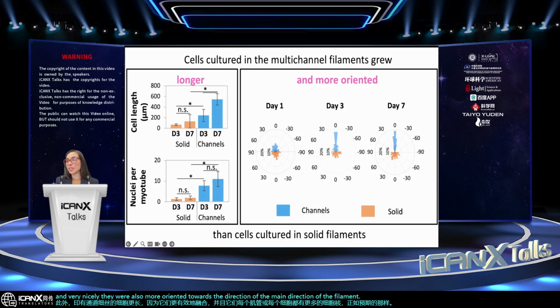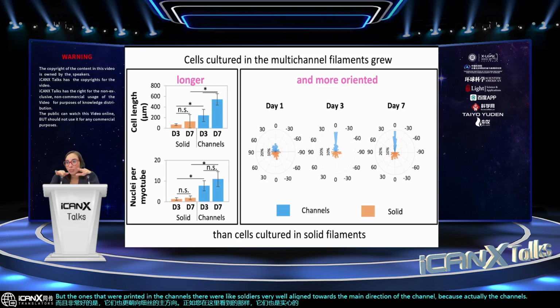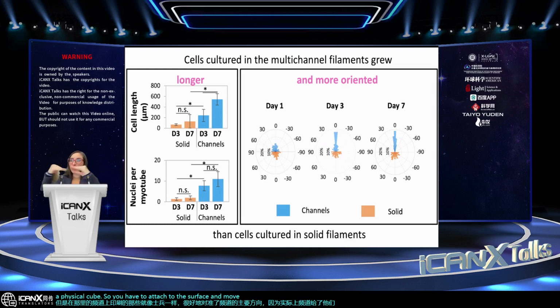As you can see here, the solid ones were all over the place, but the ones that were printed in the channels were like soldiers, very well aligned towards the main direction of the channel, because the channels give them that physical cue. So you have to attach to the surface and move that way and merge with your next cell neighbor to make a strong and solid myotube. So we saw what we expected, happily.